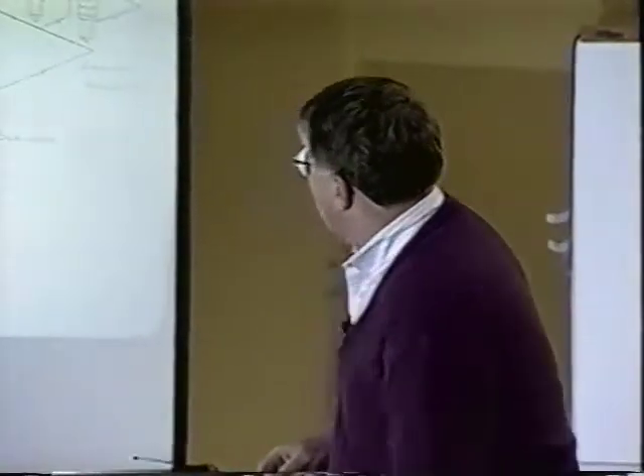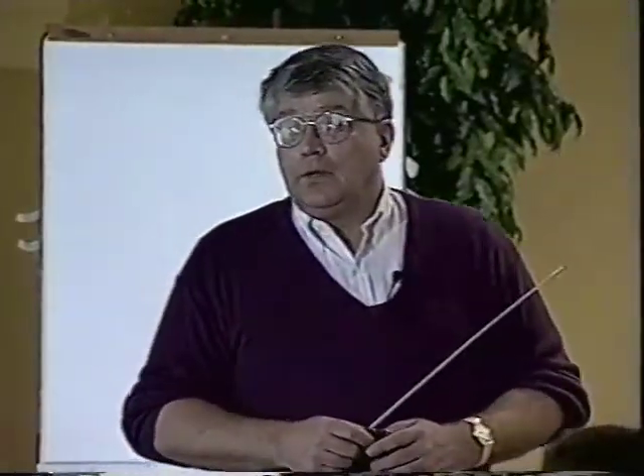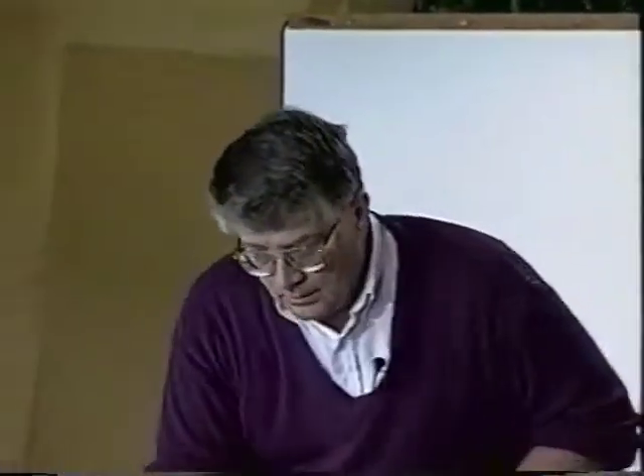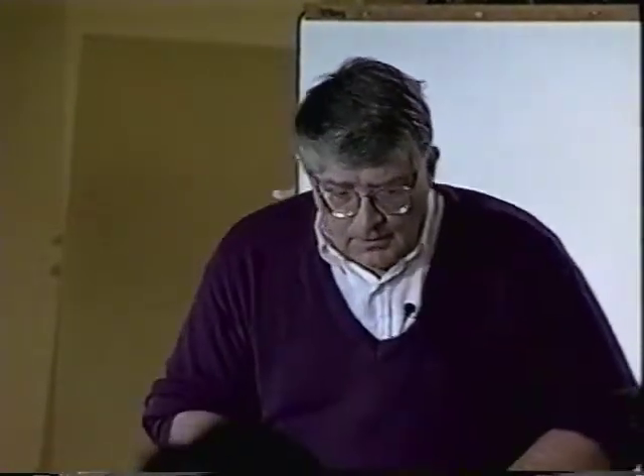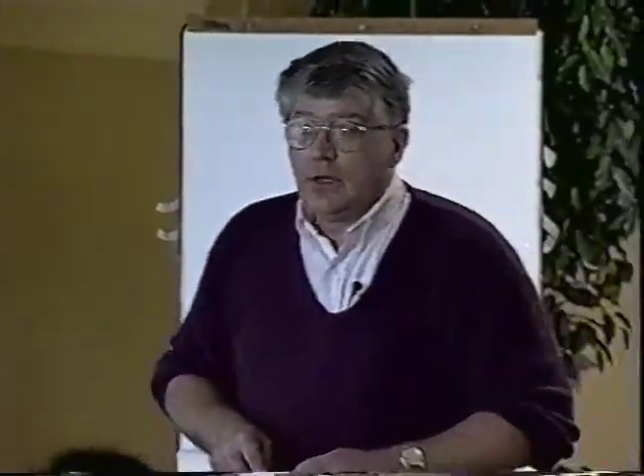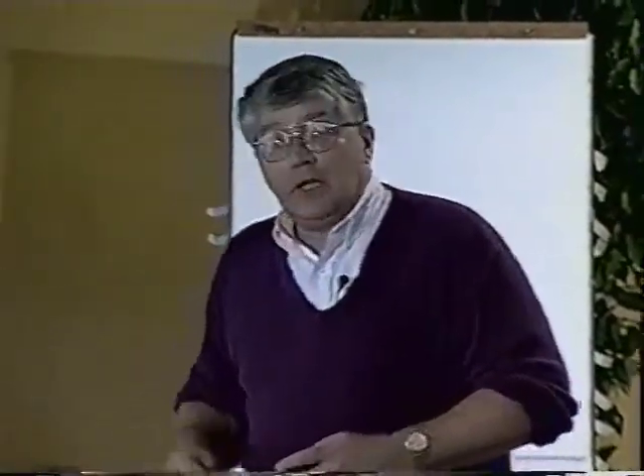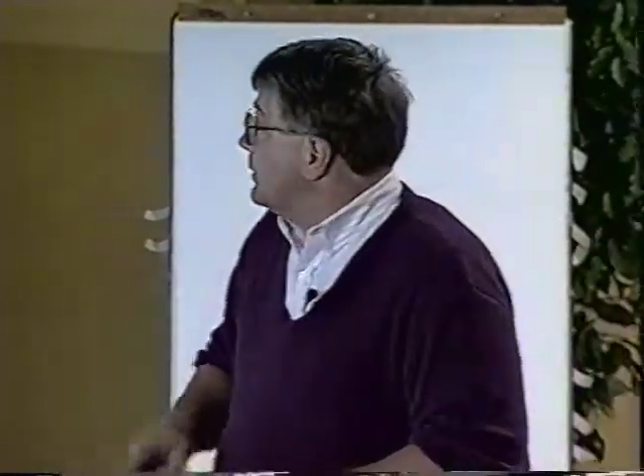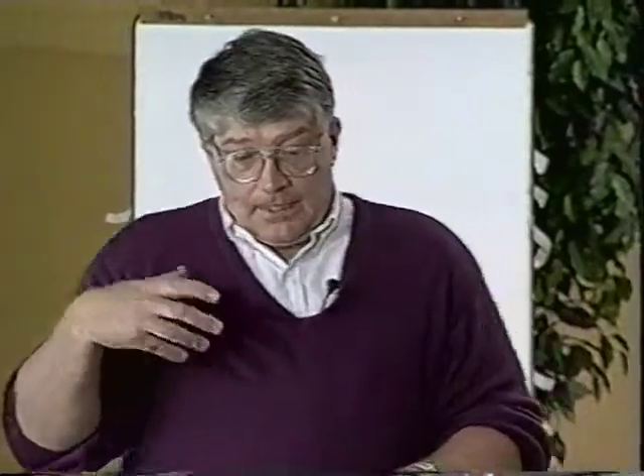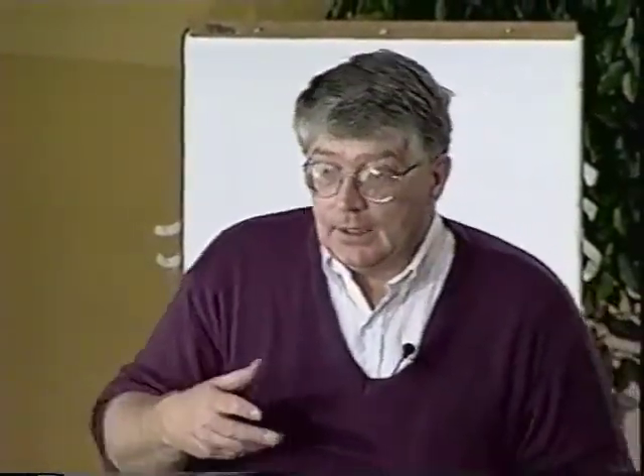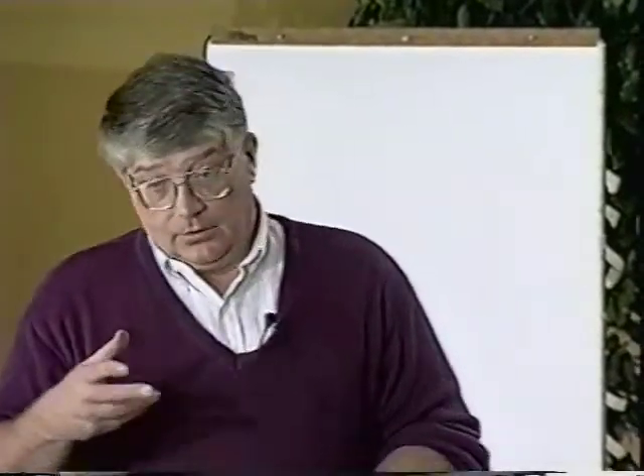Okay. Are there any questions about the coke oven? Yes, sir. I saw your materials and your utility bill. It seems very low, $300,000 a year. Is that because you usually allow the products to fire? Very much so. About 80% of everything used in the mill comes from the coke ovens, either in the form of coke for fuel in the furnace or the gases we use or make in the coke battery, yes. And the thing about the coke oven gas, it has a BTU value of about 540. Natural gas has a BTU value of about 1,000. So, you know, it's not a bad gas.